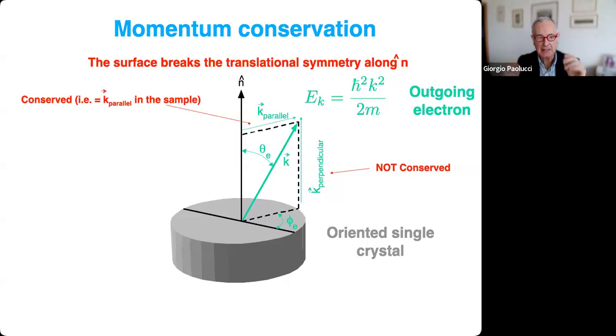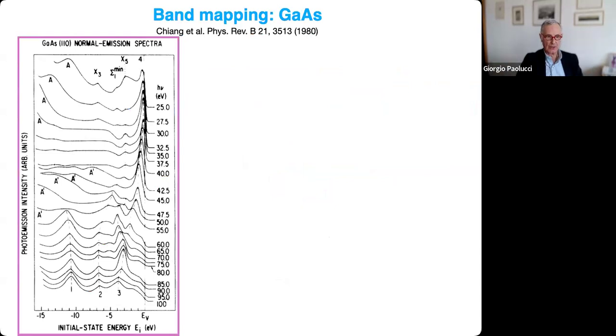Now, if you remember what I said, that the electron has to overcome a potential barrier to go out of the sample, you can easily imagine that the perpendicular component of the wave vector is not conserved in this process. But nothing happens in the direction parallel to the surface. So that component is conserved. And that means that you can actually map the energy. And this is one of the first applications of synchrotron radiation. This is very old.